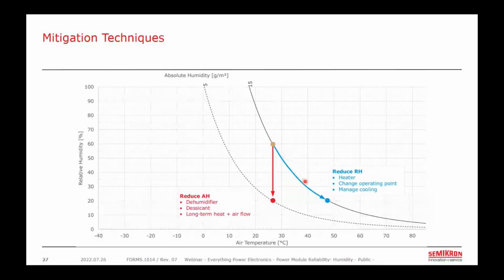And in doing so, we move down along this absolute humidity line to a lower relative humidity, in this case from 60% down to 20%. Or alternatively, if we can remove the water vapor that's present in our system, we can change the absolute humidity, and we can jump from this higher line down to this lower line while maintaining the same 25 degrees C. So in both of these cases, we've gone from 60% down to 20% relative humidity, but we have different amounts of water molecules in the air. In this second case in red here, we've actually dried the air by removing the water molecules. And it's really important to notice here that raising the temperature alone doesn't necessarily dry something out, since the water molecules might still be present even though the relative humidity has dropped.